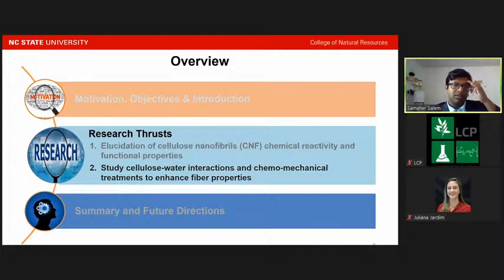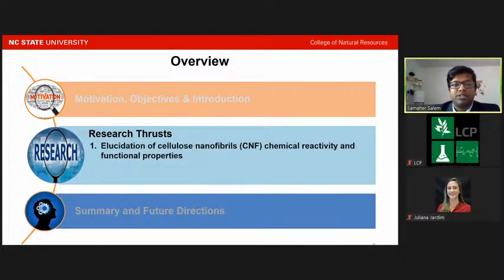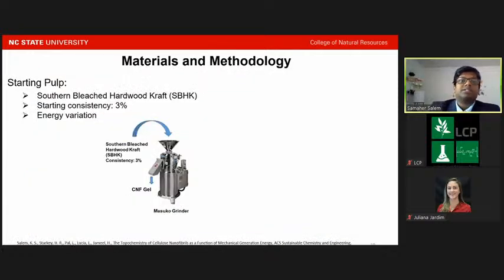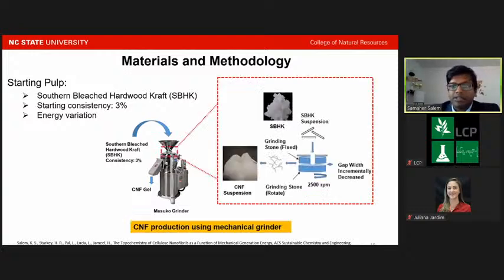So now the first part of the research, which is the elucidation of the cellulose nanofibrils' chemical reactivity and functional properties. My starting material was southern bleached hardwood kraft pulp, and the starting consistency was 3%. I used the Masuko grinder and varied the energy using different passes to produce the nanocellulose. This is the schematic representation which shows the production of the CNF suspension, where I passed the pulp through the grinder, where one of the grinding stones rotated and one was fixed, and decreased the gap width incrementally so that it could grind the cellulose fibers to nanofibrils and produce the suspension.